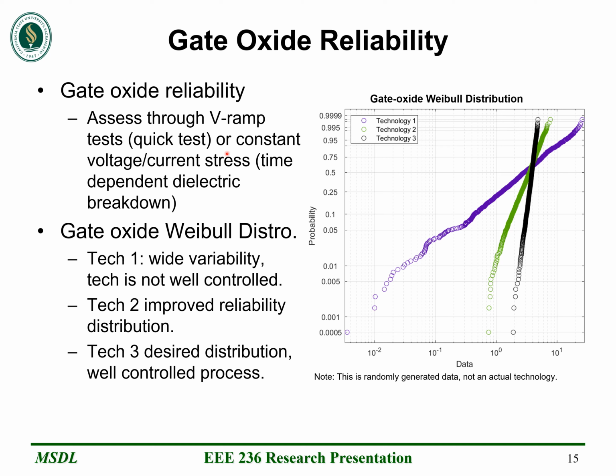Alternatively, there is the constant voltage or constant current stress, which is typically used during time-dependent dielectric breakdown studies. Under this test, you apply a constant bias on the gate and again monitor the leakage current. As time passes, the leakage current will continually rise and eventually snap for certain technologies. Again, this is an indication that your oxide has broken down completely.